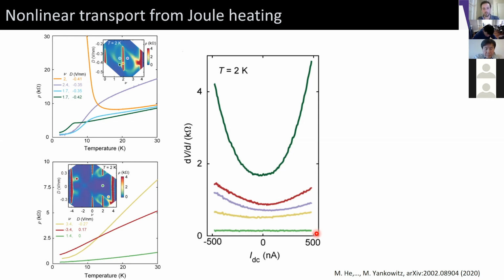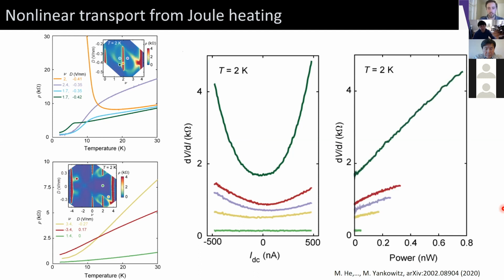Now, again, this doesn't really look like superconductivity in the sense that we don't have sharp quasi-particle peaks, and we don't have saturation to a fixed normal state resistivity at high applied DC current bias. Instead, I think this is a consequence of Joule heating. And the reason that we believe that is just a consequence of plotting this as a function of the dissipated power in the system, so basically the voltage times the current. And what we see is that the more nonlinear the transport is, the more power they're actually dissipating.